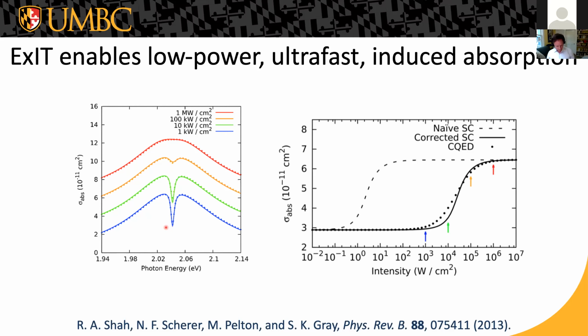But if you just shine continuous wave radiation on this coupled system and look at how the scattering spectrum, or in this case, the absorption spectrum, evolves as you turn up the power, you see that this dip, the induced transparency, disappears. And the mechanism is pretty straightforward. You're just saturating the transition of the quantum dot. So its transition dipole moment, when it's saturated, goes to 0. So it's no longer coupled to the plasmonic system, and this induced transparency is no longer there.